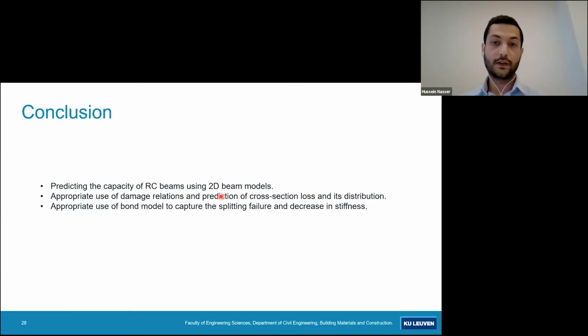Therefore, the use of a 2D beam model can predict the capacity of RC beams, and the use of the damage relations related to the cross-section loss should take into account the distribution of pits in order to calibrate such relations. The model is able to predict the behavior to a certain degree of accuracy, yet the improvement of the model should take into account an improved bond model in order to capture splitting failure and the decrease in stiffness.